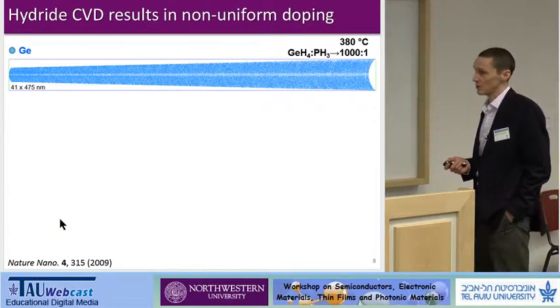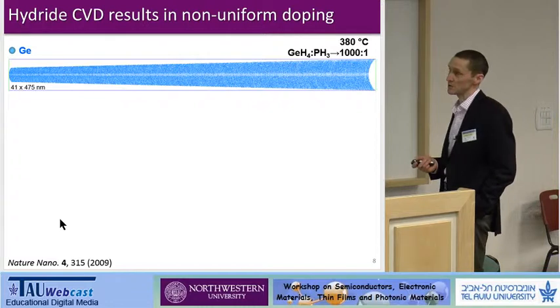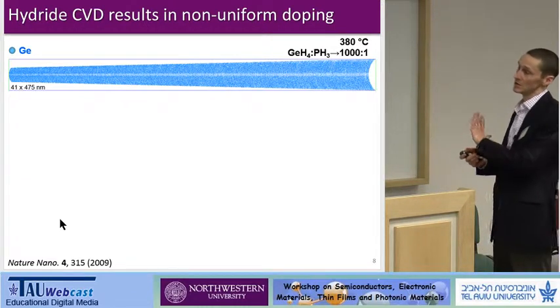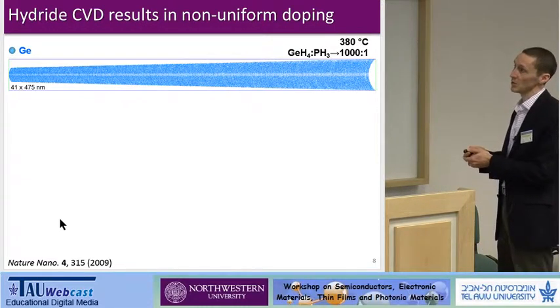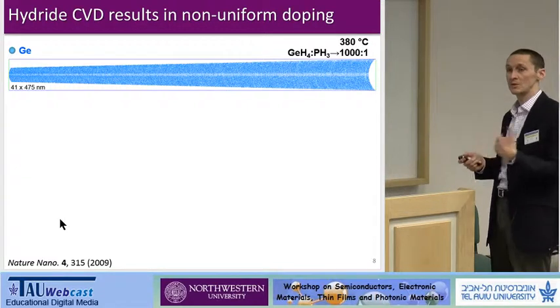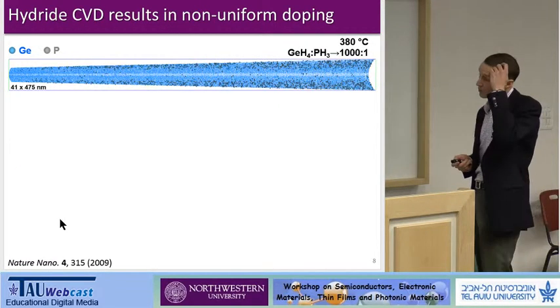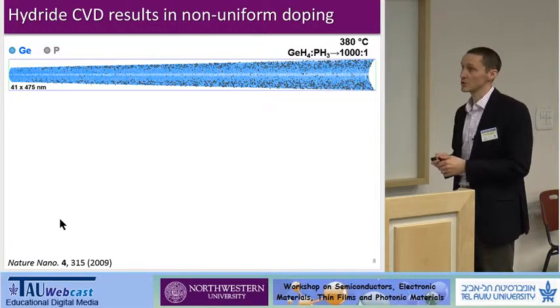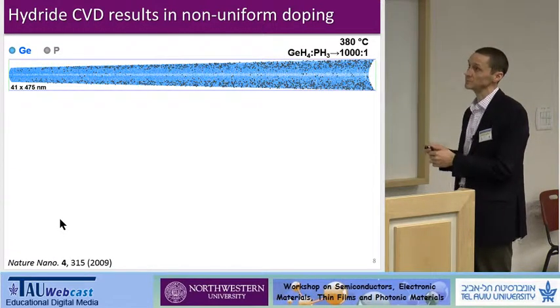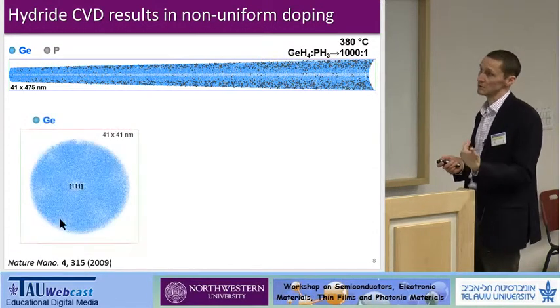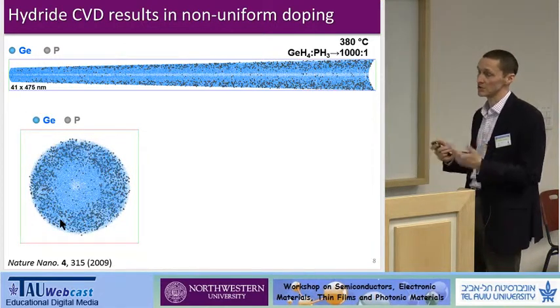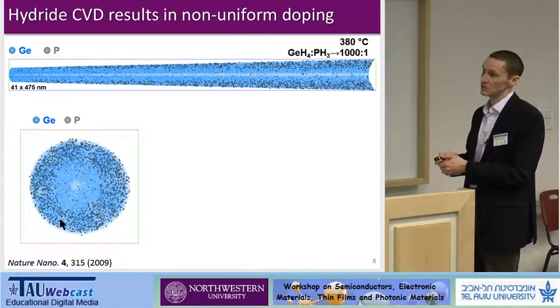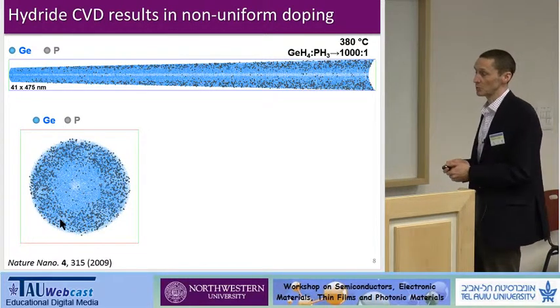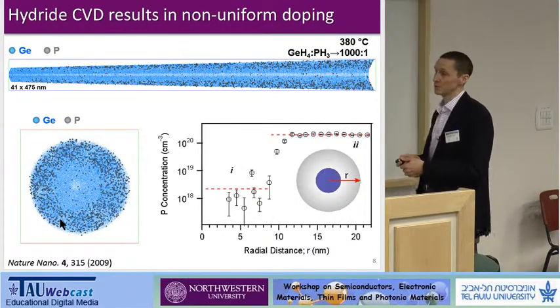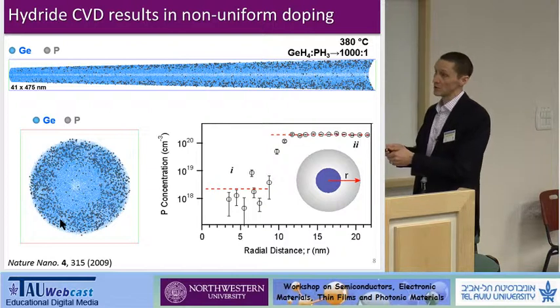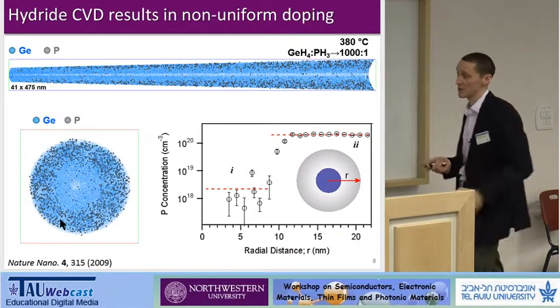Now we turned our attention to doping fairly early, to understanding dopant incorporation processes. So this is a slice through the germanium nanowire that's been grown in the presence of phosphine, which should be an N-type dopant. And what we found is an enhanced concentration of phosphorus towards the outside. And if we look down the center of the wire, you can get a better sense of the geometry. Essentially, there's a less doped region in the middle, a more highly doped region in the outside. Quantitatively, we can extract profiles from the center to the outside, put numbers on it.